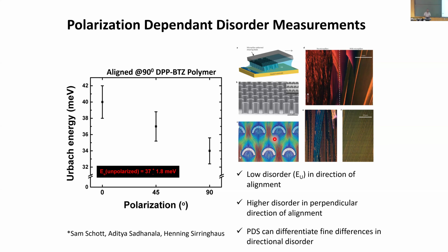Now if you take that as a sample, along the growth direction you will have better crystallinity, so you expect better transport. Perpendicular to the growth direction, you don't expect better transport. So that is precisely what you see here.